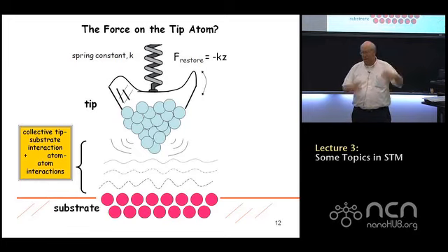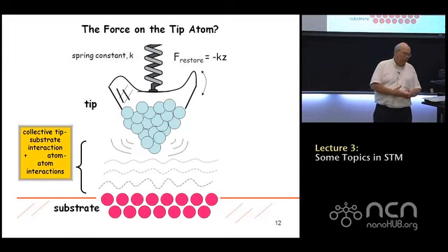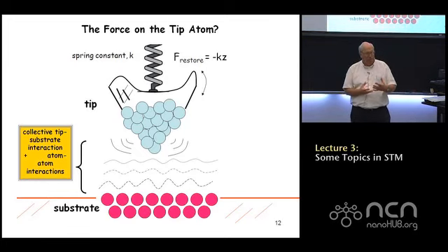The electric field between the thundercloud and the earth is on the order of 10^7 volts per meter. That's enough to make your hair stand on end, right? But 10^9 volts per meter is a factor of 100 higher. And those fields can be achieved in the laboratory environment, but they're strong enough to actually rip atoms off the tip, right? They just field desorb. The electric field is high enough that it desorbs atoms from the tip.